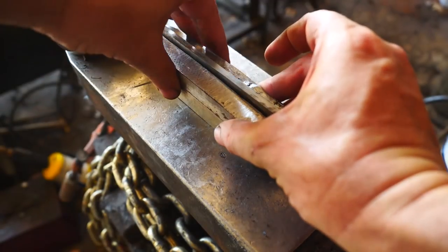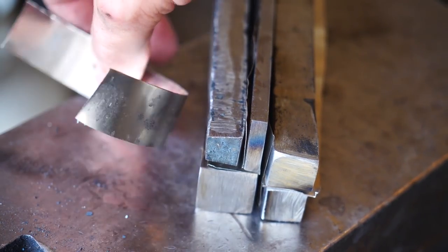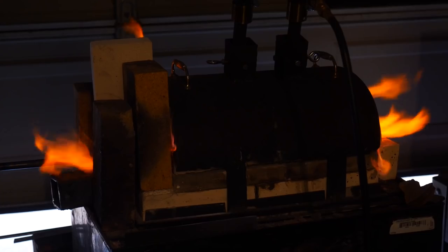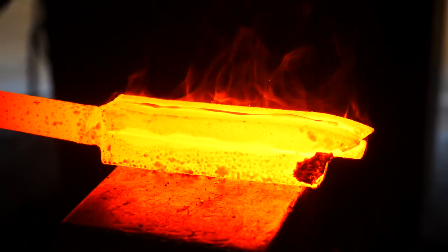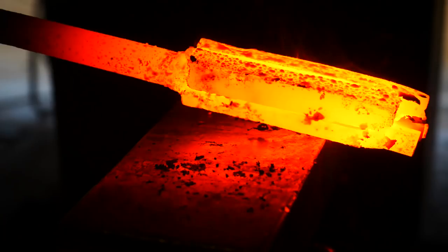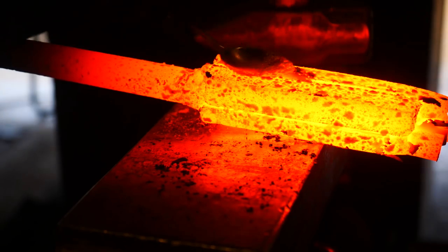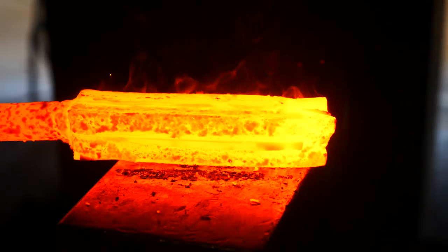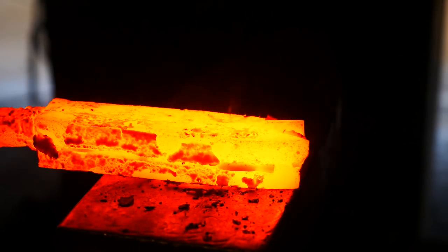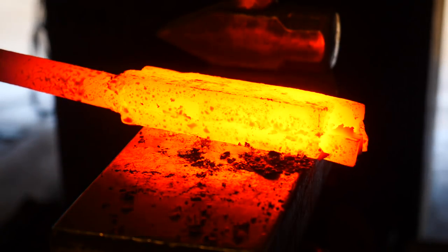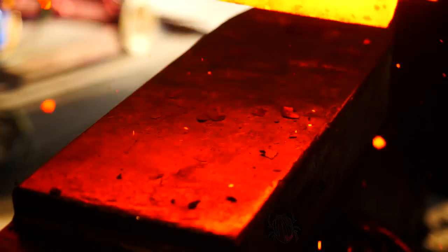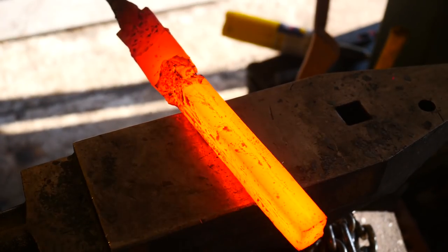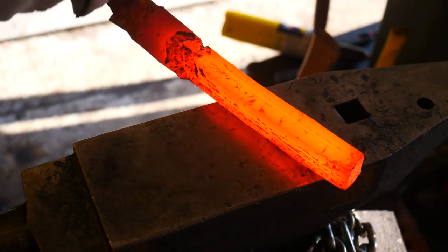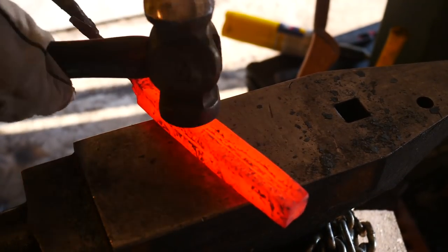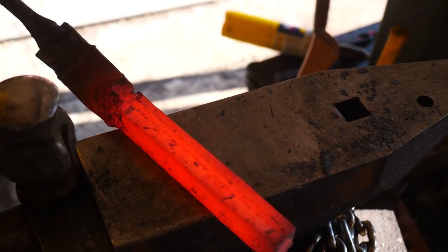This is a piece of 1070, another piece of high carbon steel. Sort of evens out the block. We'll put some nickel sheet in between them all. That will etch very brightly. Try to get this all forge weld together, twist it up, and we might have a pretty decent pattern. So you saw me applying flux and then hitting it with a hammer, and we're slowly getting it welded together and drawn out. Pretty soon we'll start rounding the corners a little bit, and then I'll take it over to the vise and we'll twist it.